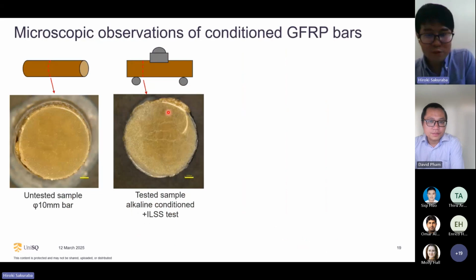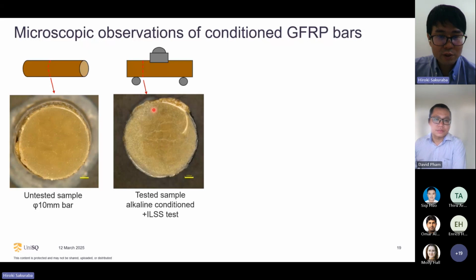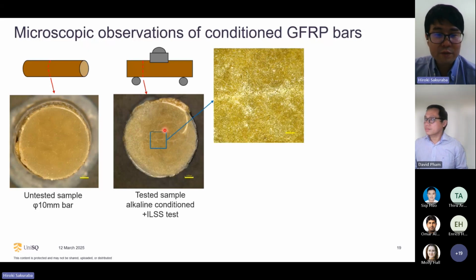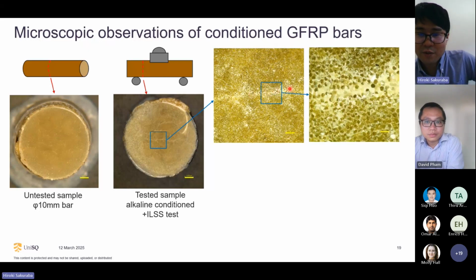And I'd like to share some examples of GFRP bars. This shows an untested sample of a 10 millimeter bar, and this shows after alkaline conditioning and interlaminar shear strength test. We have some damage area, and also horizontal cracks due to the interlaminar shear test. If we observe this area, we can see the crack at high magnification. And at even higher magnification, we can observe the damage between the glass fiber filament and resin.